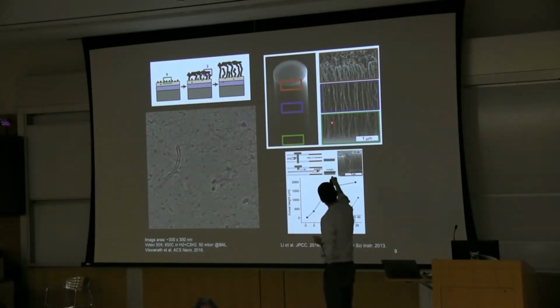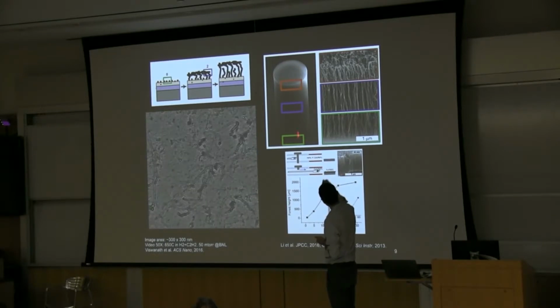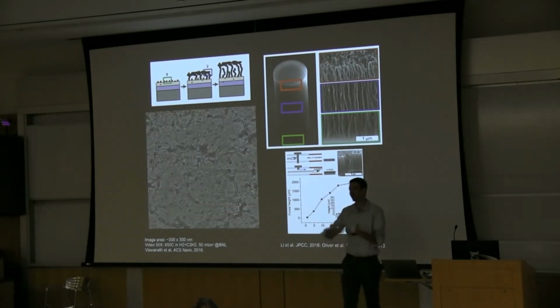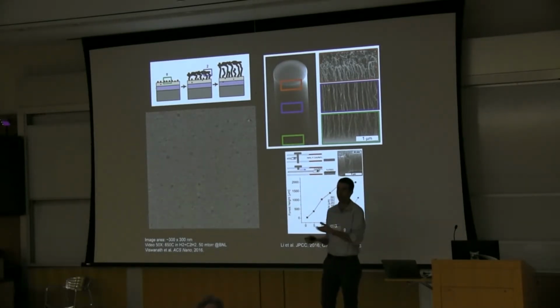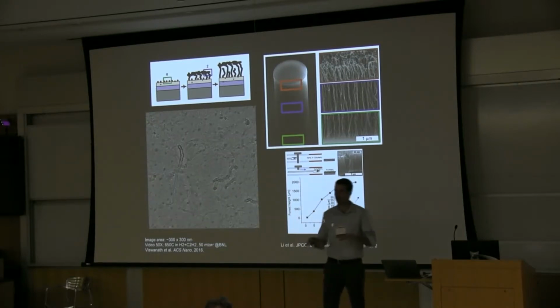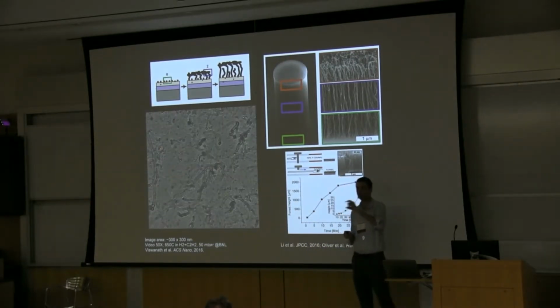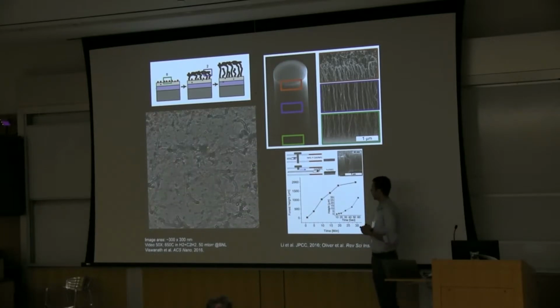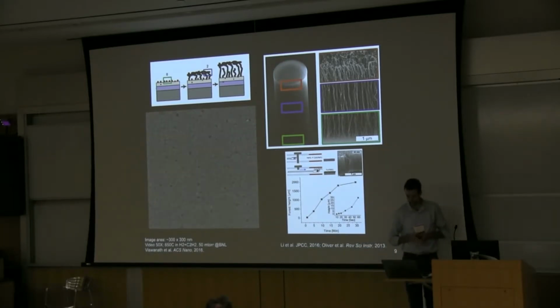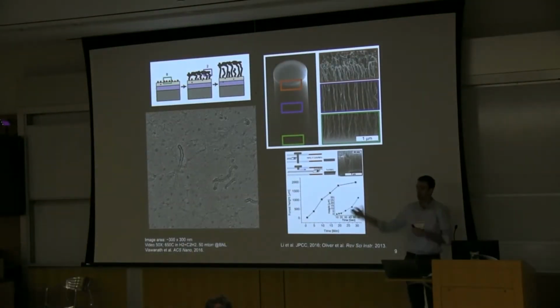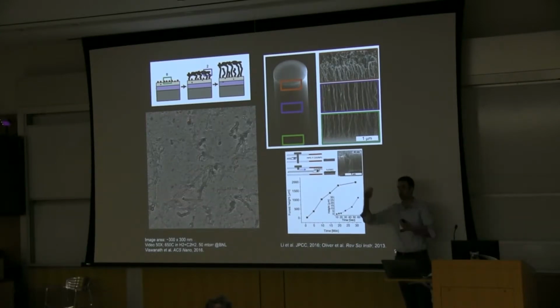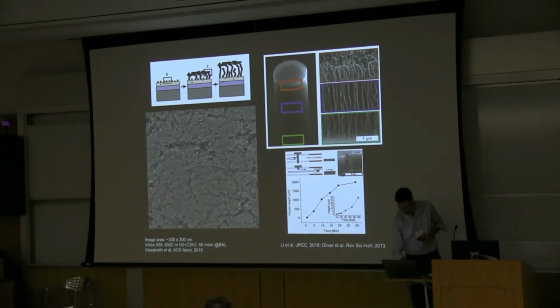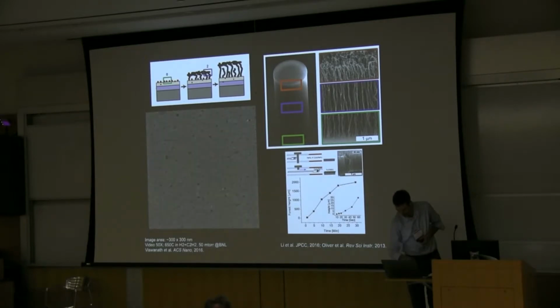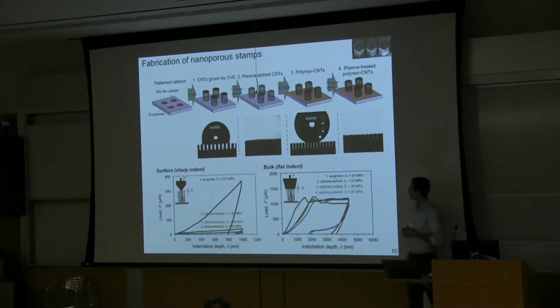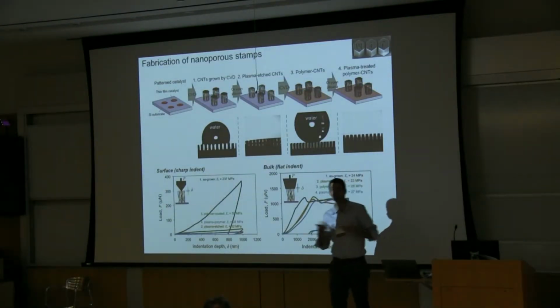photolithography. They are microscale in height and foam-like, and if you control the gases in your furnace rapidly and insert and remove the sample, you can grow structures to tens of microns height in a matter of 1 or 2 minutes. So it makes the process fairly efficient, and if you want to grow them much taller, not for stamps but other applications, you can grow them up to a couple millimeters with limitations due to the catalytic lifetime. In order to make the nanotube forests useful as stamps, we need to do some engineering.